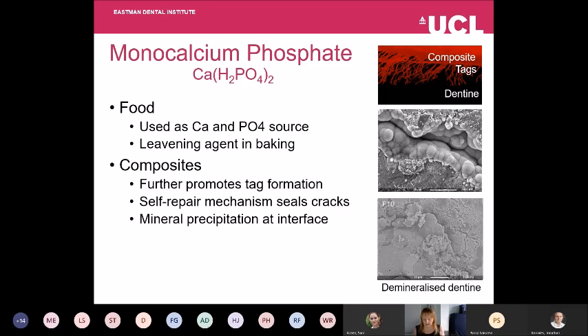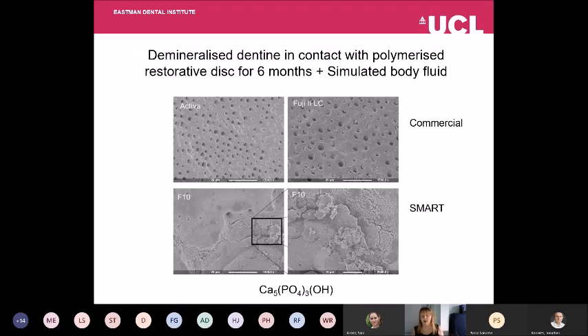Additionally, if we place our material in contact with demineralized dentine and then take it away, what we see over time is that we have mineral precipitated at that surface. If we do this with commercial materials like Activa or Fuji II LC that release fluoride, we don't see anything at the surface. So we've placed these polymerized materials on top, in contact with the demineralized dentine. Smart material gives this layer of calcium phosphate after 6 months, which can help us to seal up any gaps that might form over time.